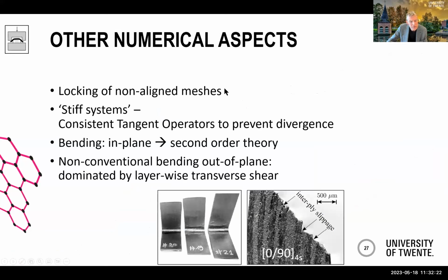Due to the extreme anisotropy, you cannot just place your fibers in any direction. It's most secure if you align your mesh with the fiber angles. Otherwise, silly things happen. There are few elements which can work with non-aligned elements, but these are really few. Further, the large difference in stiffness or compliance in the different directions leads to stiff systems. So to get these things convergent, you definitely need consistent tangent operators. Otherwise, it's very hard to achieve convergence.